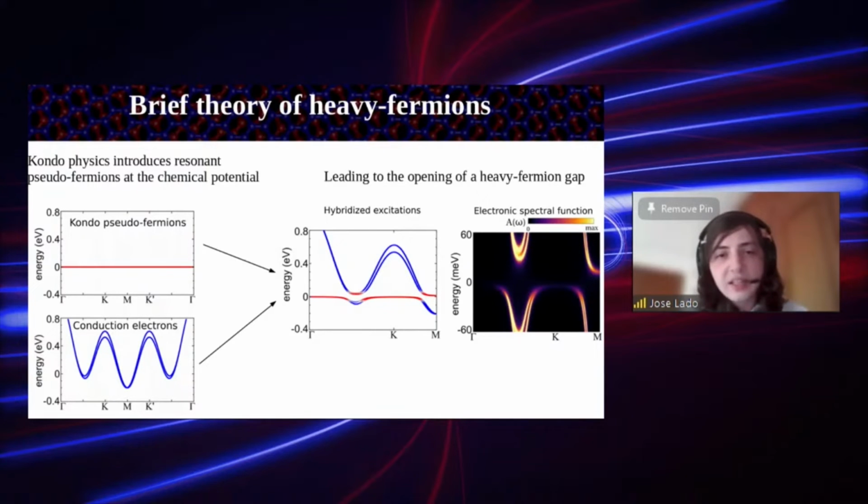The basic idea is that when you are in the right regime between Kondo coupling and exchange coupling, your Kondo sites can be replaced by pseudo-fermions, so fractional spinons, and your conductive electron gas remains a conductive electron gas. And the Kondo coupling essentially couples your pseudo-fermions coming from the Kondo sites with your conductive electron gas. In short, what happens is that you get a gap opening at the Fermi level. So a system that originally is a metal becomes an insulator because of this Kondo coupling.